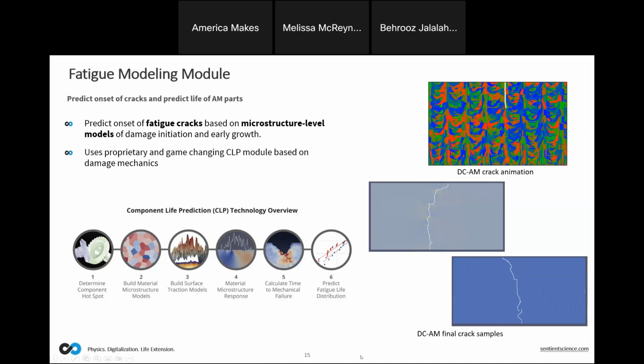not only the fatigue life itself, but also the crack pattern is affected by the microstructure of that specific domain. When you're running 30 domains, all of those 30 domains have the same average statistical behavior in their microstructure, but in details, they are different. And those differences in the details are causing that variation in both fatigue life and the crack patterns.